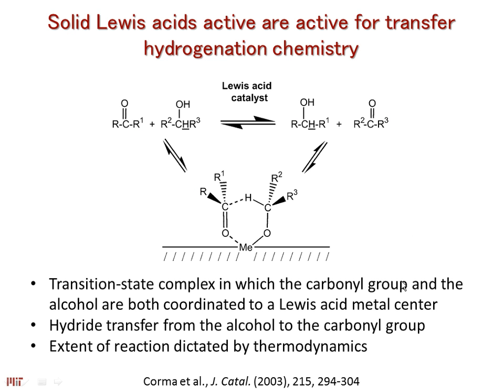So we take a look at some of these materials, which have been described in the literature before. Avelino Corma was the person in Spain who pioneered some of this chemistry, and he found that some of these zeolites containing, for example, tin or zirconium, were very active hydrogen transfer catalysts. This reaction is called the MPV reaction, and it's a way of changing functionality from a carbonyl to a hydroxyl. You have these two molecules, and they flip functionalities through a transition complex around this active site that can accept two sets of oxygen atoms. What you have then is an intermolecular hydride shift, so you pretty much shuttle hydrides between molecules. But that is something that can be exploited in many different ways.